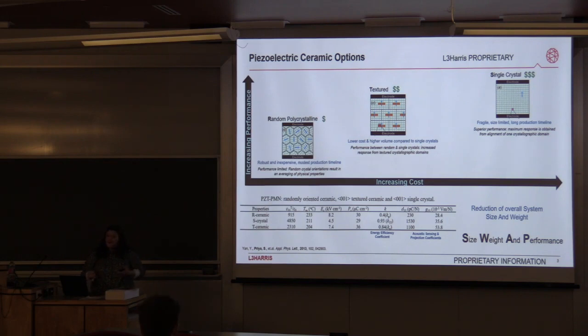Also, it's quite expensive to grow single crystals. To have a facility that makes many of these, you're looking at a month just to make one single crystal. And while it has these fantastic properties, that's quite a bit of time. And then also, it's usually grown by the Bridgman growth method, which utilizes platinum crucibles, which again, if you're going to grow single crystals, you're going to need to have your own facility to refine these crucibles as well. So that's some of the limitations.